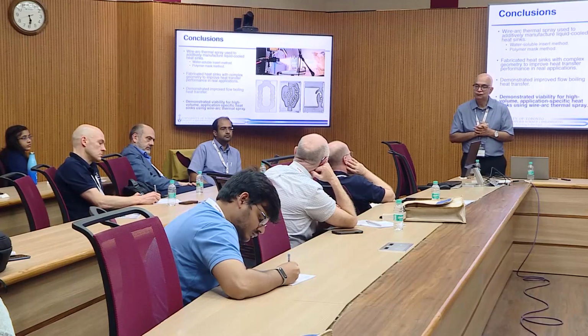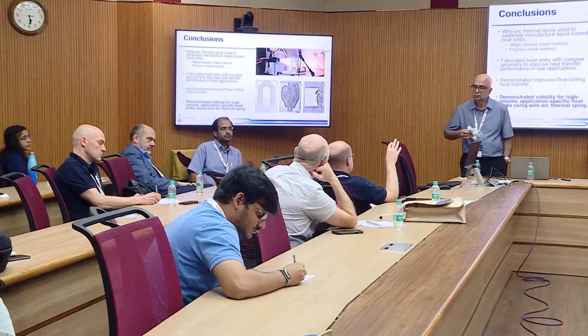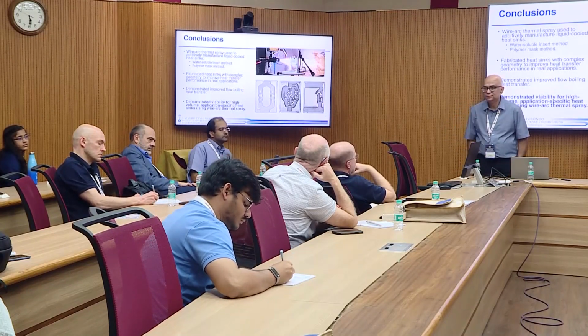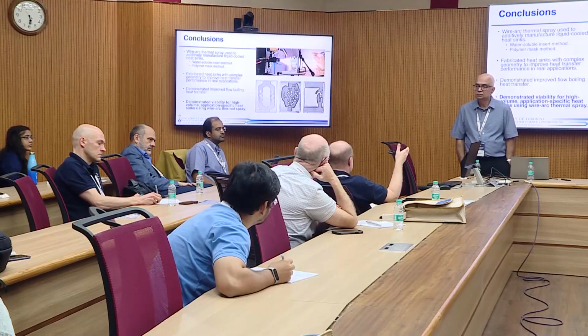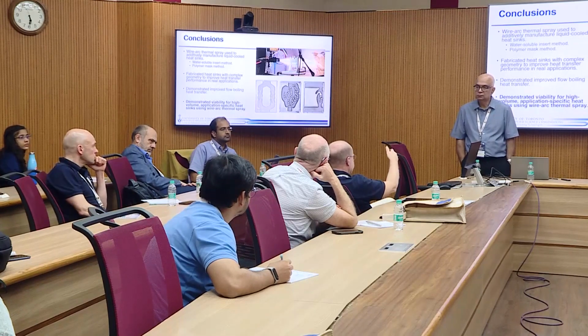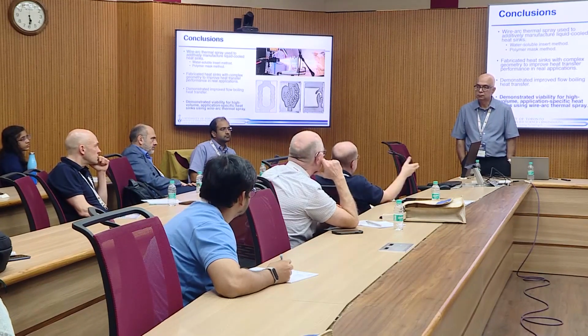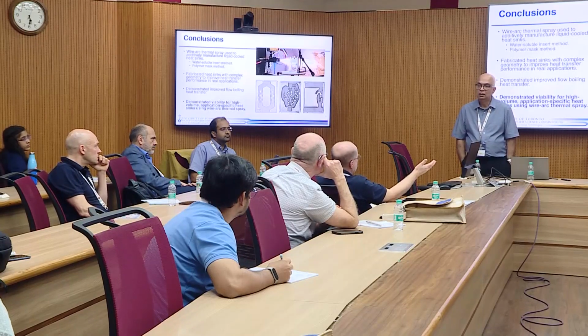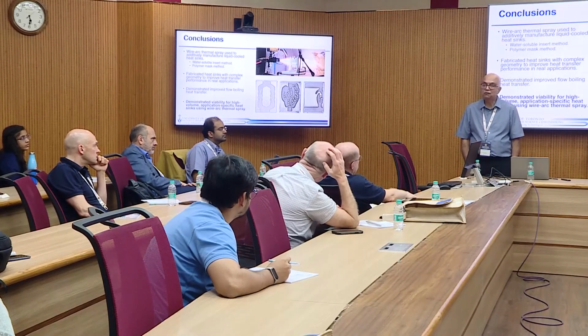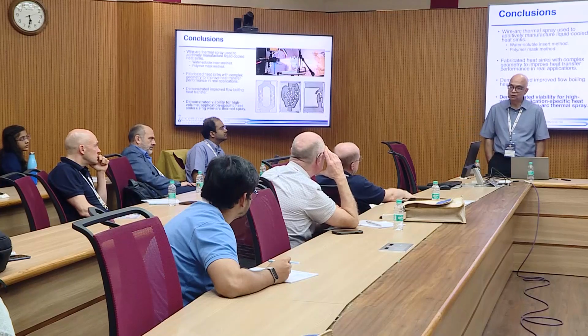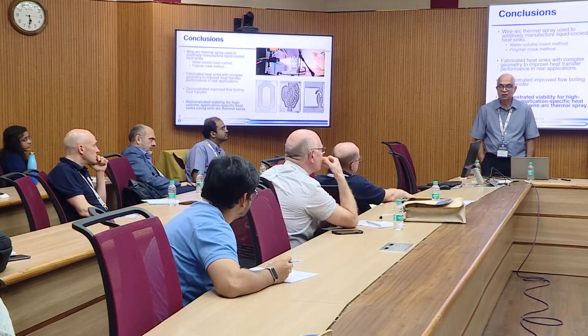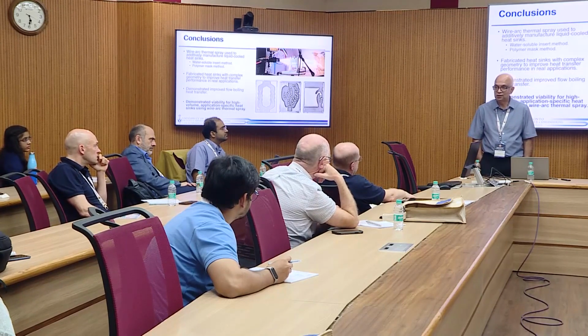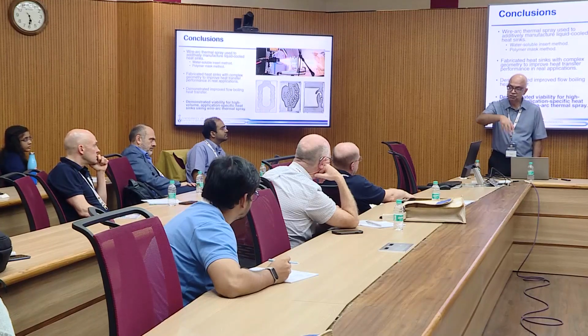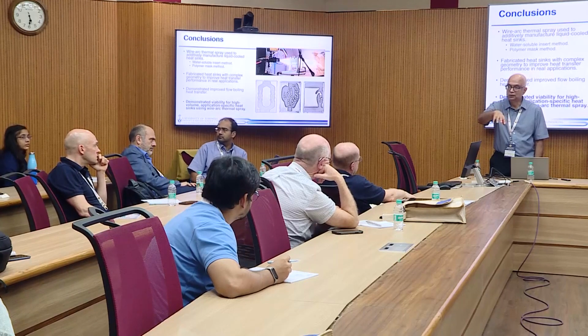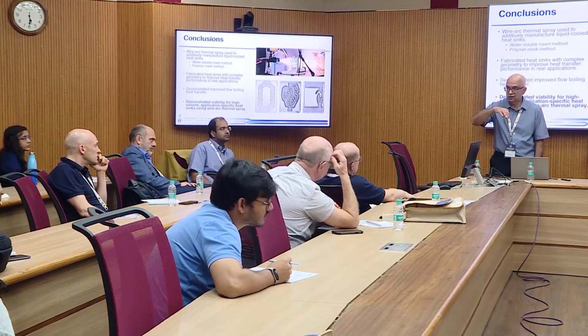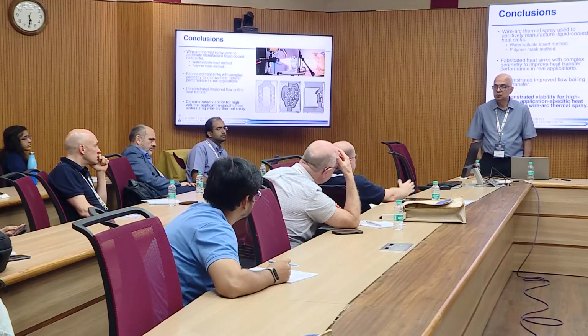Very interesting technique. The typical size of your channels is a millimeter. Of course you get this porosity, which is an excellent feature. But could you simply drill it, if you calculate how the flow should be distributed? Then you don't have the porosity, but it's maybe a cheaper process. No, if you go and talk to your machine shop and ask them to mill out one of these things, they will ask for a month and they'll charge you a lot of money. We've tried that. Even machining straight channels is an expensive process. Using milling or EDM or something like that, at millimeter size, it's typically easy to do.